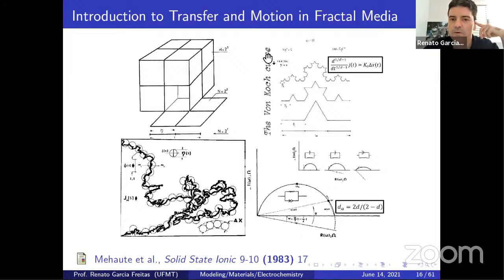So for the first time, the von Koch curve was observed here, and this equation was used to insert the alpha parameter in the impedance. Take a look here in this circle. This circle can be considered as the N, so every circle you see is the N repetition of this one. You have delta X of an entire circle, like the circle goes together, makes some curves and goes straight. And here we have a stochastic dimension of the lithium diffusion on the carbon porosity, like the very first slides I showed you from the carbon energy and battery capacitors. And this work studied fractal dimension in electrochemistry as well.